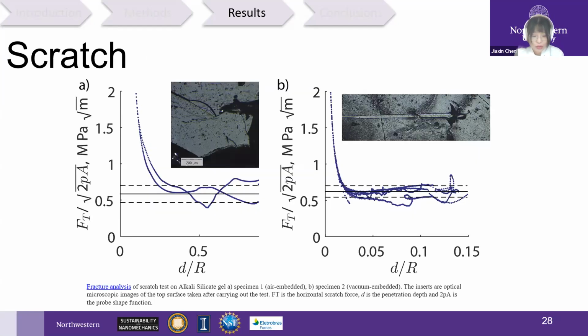The scratch test intrinsically involves a combination of ductile and brittle failure. Therefore, by calculating the geometry, with depth to tip radius ratio going to infinity for tests with axial symmetry at symmetrical probes, we achieve a fracture-driven state that enables us to probe the fracture resistance. The quantity, horizontal force by square root of 2pa, converges toward a constant for large D/R ratios, as shown in these two figures, which is evidence of a ductile to brittle transition taking place during the test.